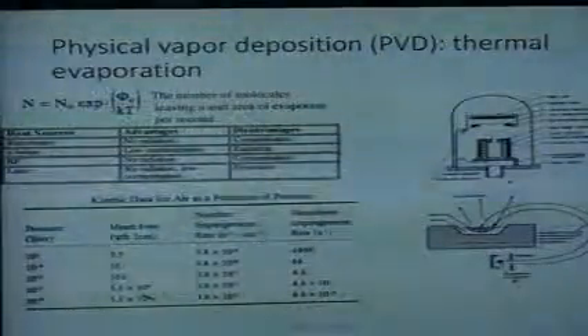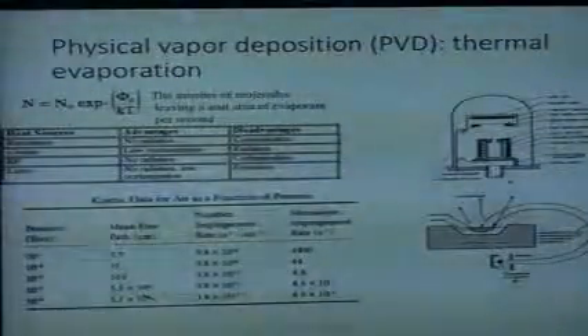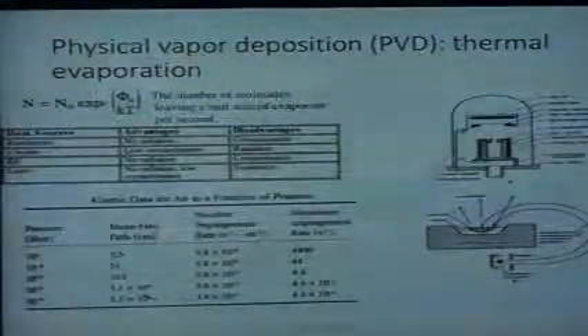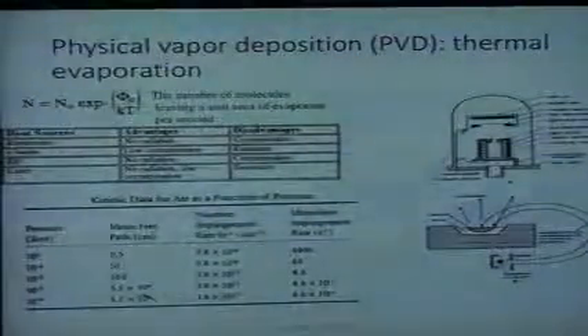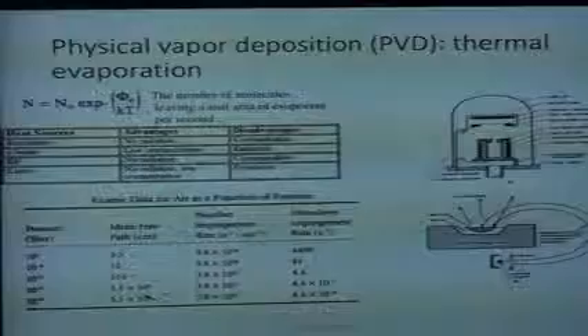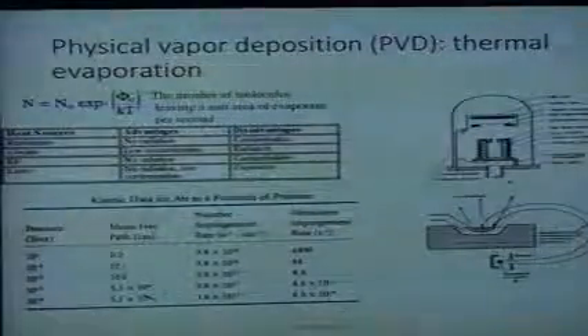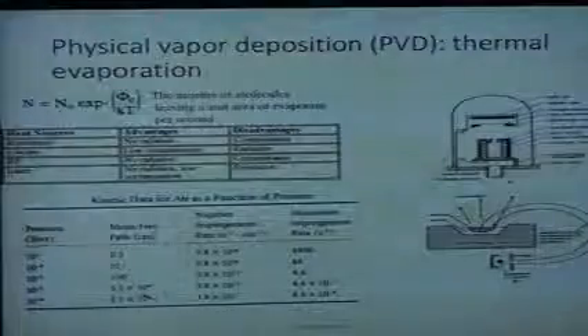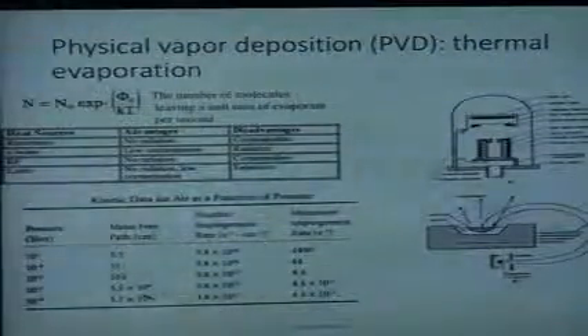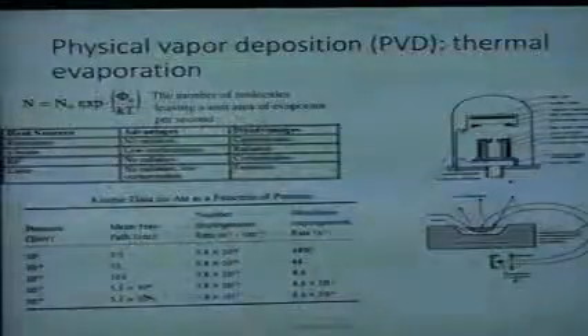Phi is an energy term. It's like a work function for electrons, but in this case it's for ions, or for molecules and atoms that come out. But what you really have to do, when you're designing an evaporation chamber, is design it so that your mean free path, that's the average distance that an atom or molecule will travel, is longer than the distance between your target, which would be down here, and your source. Okay, so that's the general idea. You want to make sure that whatever you're evaporating does not undergo a lot of scattering events along the way, because then it will start to go in places that you don't want it to go.